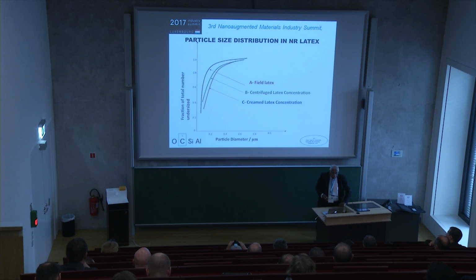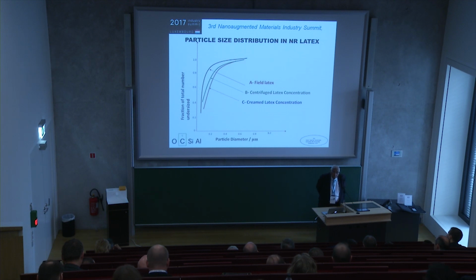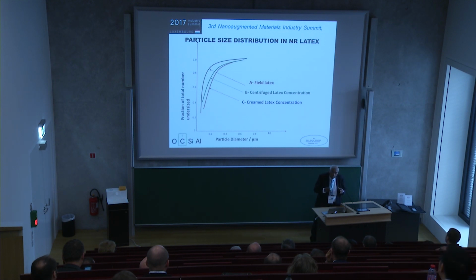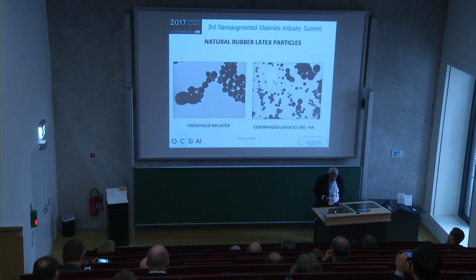When we get the field latex, you can see the first curve on the left gives a distribution of the particle size, which can be from 0.2 to 0.8 microns. And then when we centrifuge it, we throw out some of the smaller particles, and so the average particle size distribution goes up to about 0.3 to 0.4 microns. We do have processes, particularly pressure homogenization, where we can pass it through a pressure homogenizer and bring the particle size distribution back into a narrower and lower range. So particles can be broken down and stabilized at much lower particle sizes for certain applications. This just shows you the fresh field latex and a centrifuged latex.